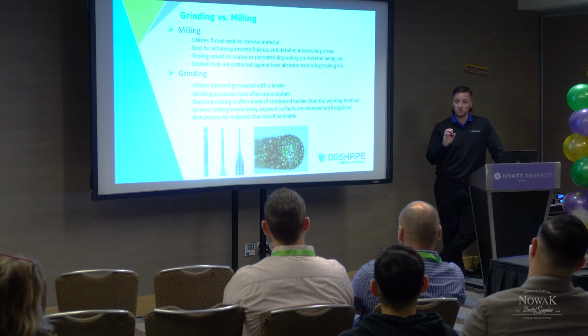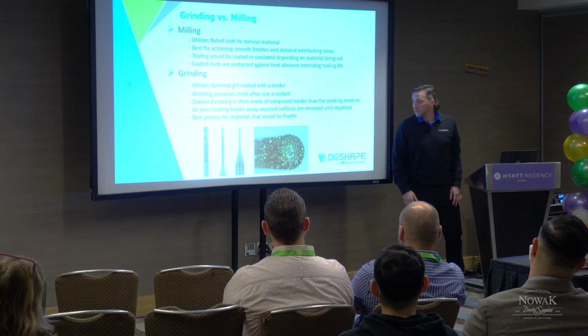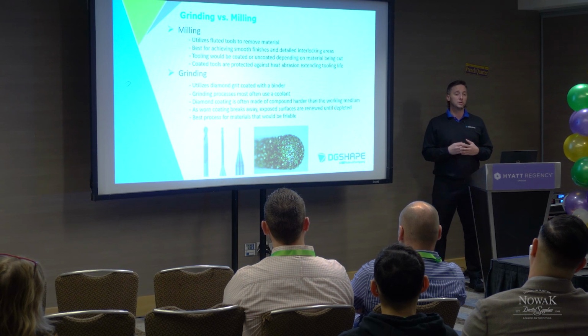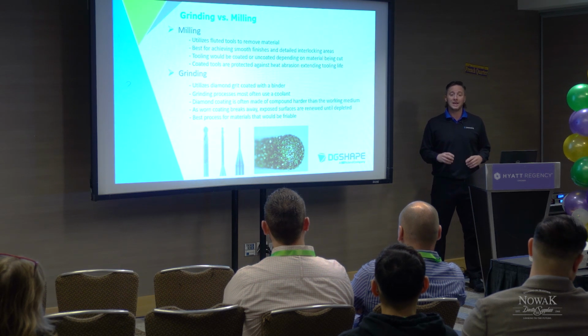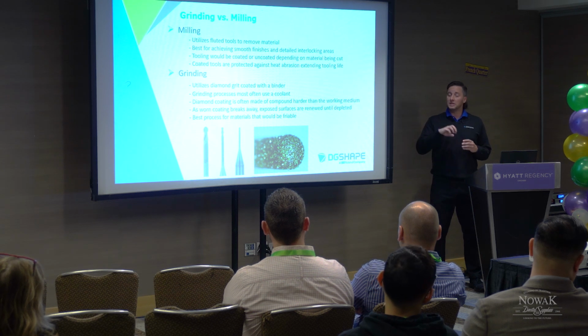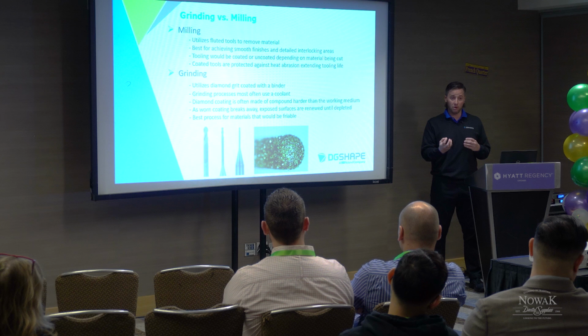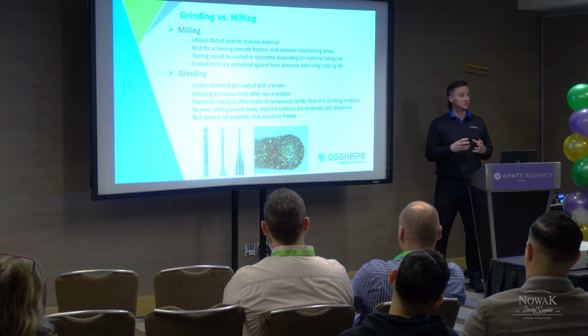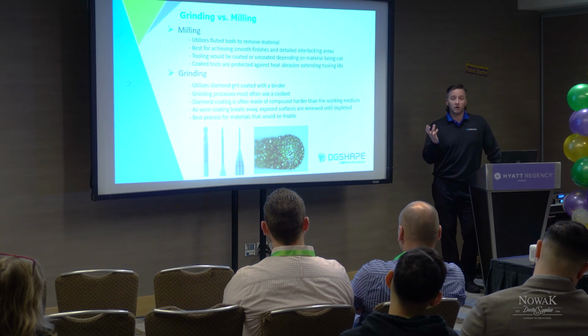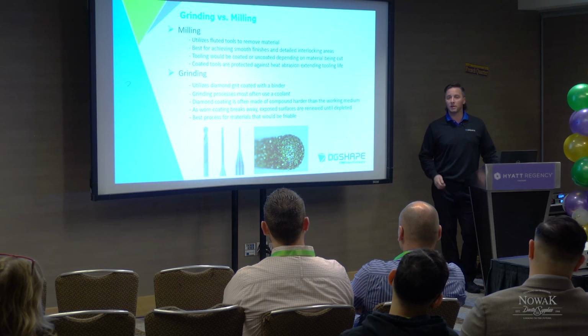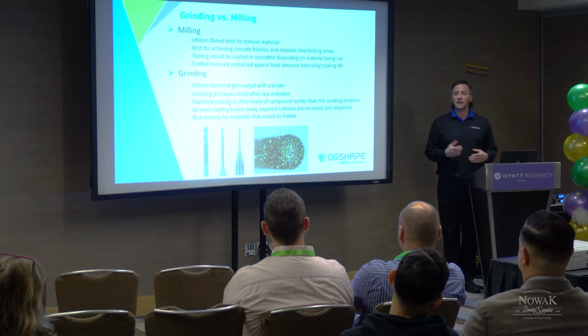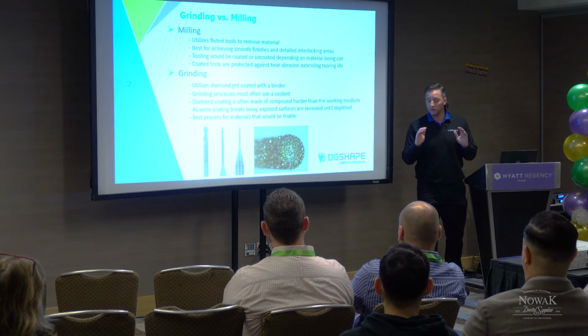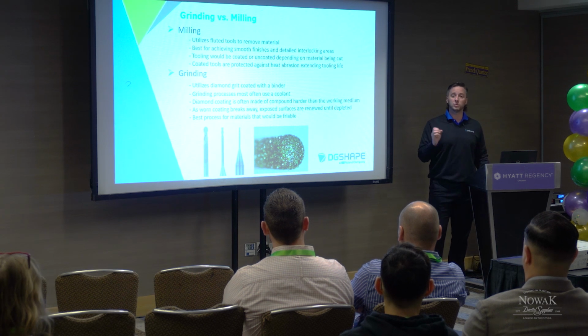The diamond coating, that grit that you're seeing there, is always made of a material that's going to be harder than the material it's cutting. It's going to be harder than that material to provide longer wear, longer use, and as those tools are used, pieces of that tooling as they become worn are going to break off, which then expose additional pieces, the layer behind that diamond coating, giving it a new sharp edge again. Think of it like taking a rock and chipping it away into an arrowhead, right? So same process. You have that coating that, let's call it a stone, that grit, and the top layer will fracture off, exposing new sharp edges.